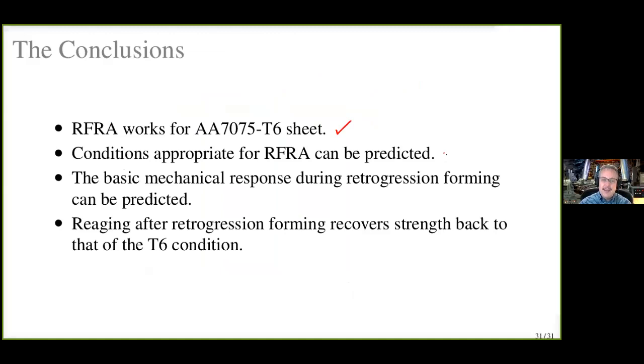We can predict the retrogression forming conditions and reaging conditions to actually make this work well. And we can at least predict the basic mechanical response during the warm forming. There are some details like forming limit diagrams we haven't pursued yet, but we can do a pretty good basic job there. And most importantly, we can do all this, make a part, and get back to a final strength that's better than the T6 condition, at least in this demonstration part.